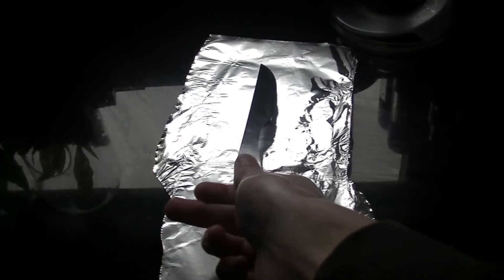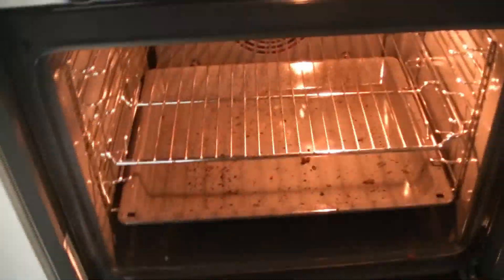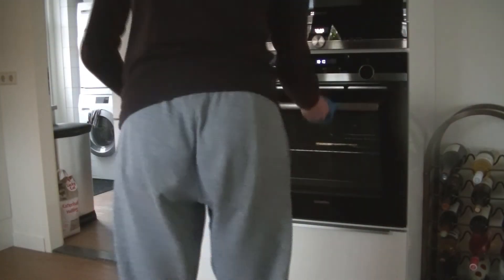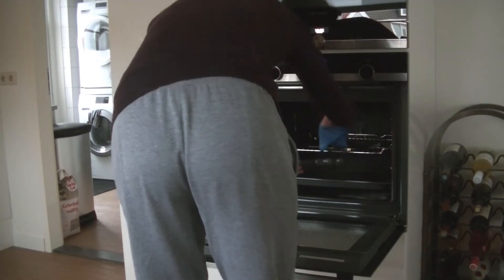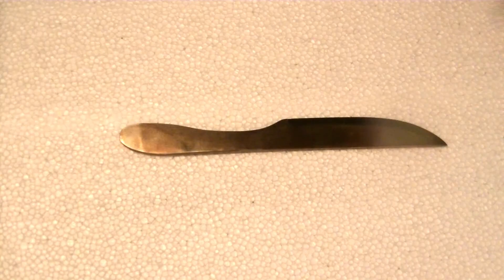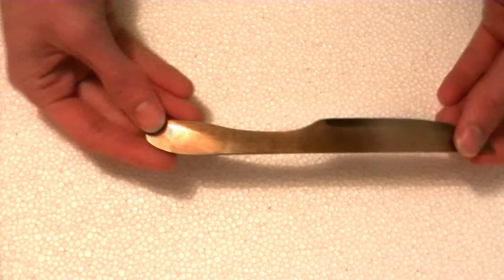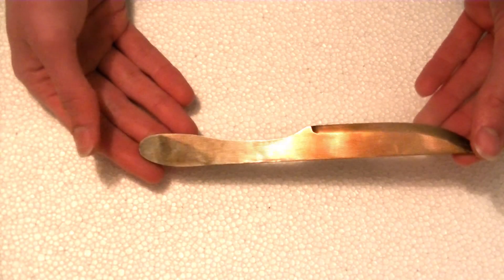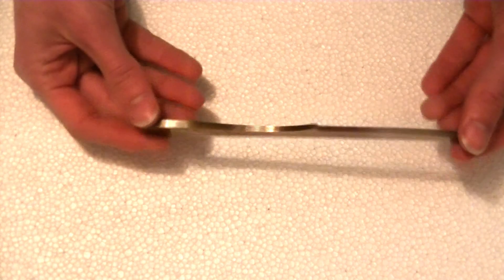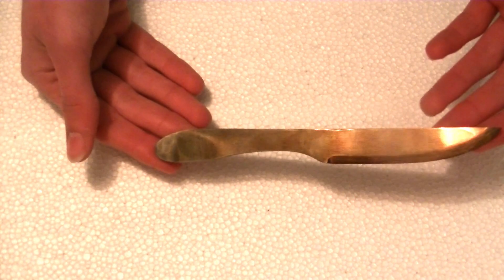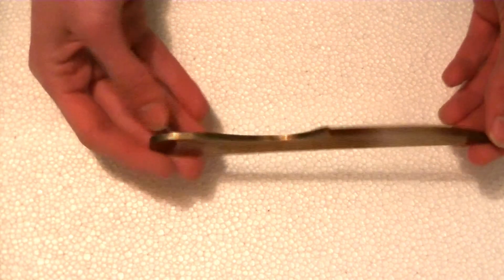I'll catch you when it's done. I tempered the blade in two cycles, each on 204 degrees Celsius for an hour. It leaves a nice bronze color, which will sand off straight away.